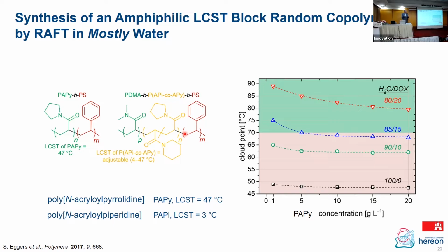So we use an AIBN-type azo initiator, whatever it is exactly, and it's thermally cleaved to generate the radicals. And this requires obviously a higher temperature. The problem now with these stimuli-responsive blocks is, in principle, that they are not soluble at a high temperature because they are LCST systems. The idea was, we start not with the styrene, which is a difficult monomer, but with this second block, so to say. The former second block in the combined polymerization strategy is now the first block in a pure RAFT strategy.